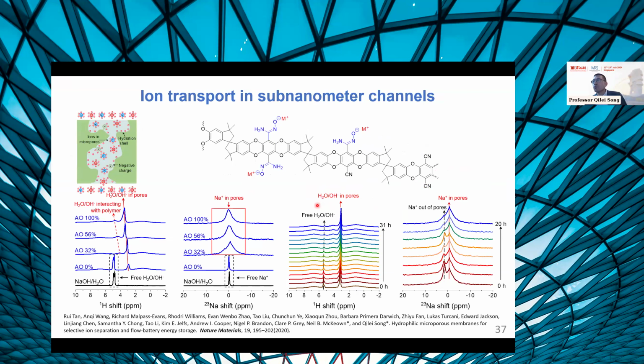So based on this understanding, we were able to demonstrate these membranes in the new generation flow batteries, as I mentioned earlier. So we use this quinone flow battery as an example to demonstrate these batteries. You can see that these PIM polymers allow the fast transport of small ions like potassium, sodium, or lithium, but they can block the large redox species like ferrocyanide ions. So then, these PIM membranes can improve the selectivity of the membranes and boost the battery cycling stability.